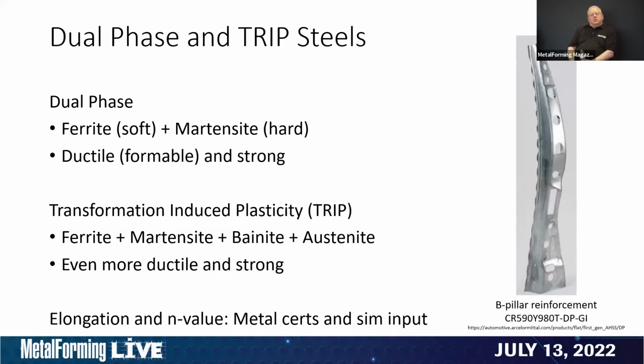Dual phase and TRIP steels are typically applied on parts that will benefit from deep drawing capabilities. They've got some draw depth to them, but we also need the high strength. The dual phase steels, shockingly, maybe according to the name, have two phases, ferrite and martensite. In dual phase steels, their hardnesses are dramatically different. Ferrite is super soft, martensite is super hard. And that is one of the things that leads to very good elongation or ductility for the strength level.